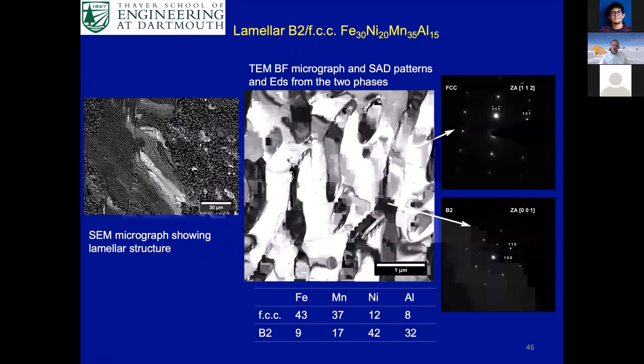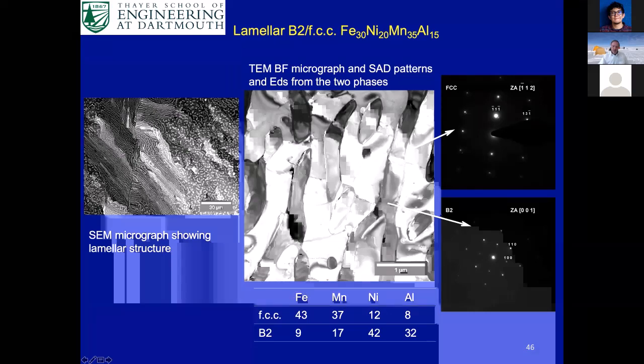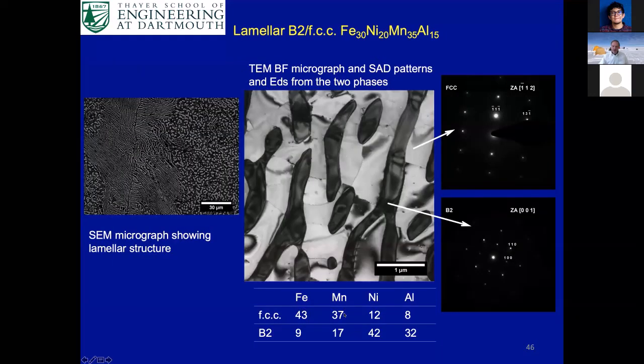So this is what the microstructure of this material looks like. This is a backscatter electron image where you can see the two phases. And this is a transmission electron micrograph. The diffraction patterns over here identify those two phases. The light phase is face centered cubic, and the dark phase is body centered cubic. And you can see that the lamella spacing is maybe about half a micron, something like that. If you do X-ray spectroscopy from the two phases, what you find is the FCC phase is very rich in iron and manganese, and the B2 phase is rich in nickel and aluminum.